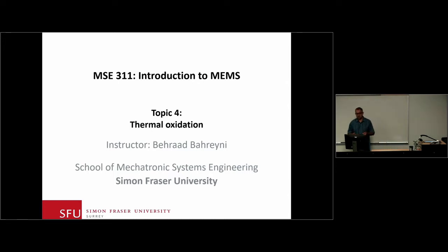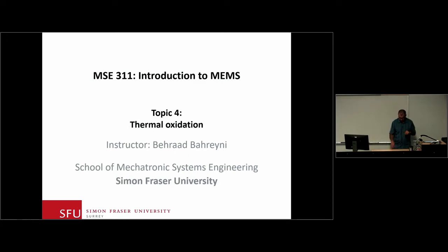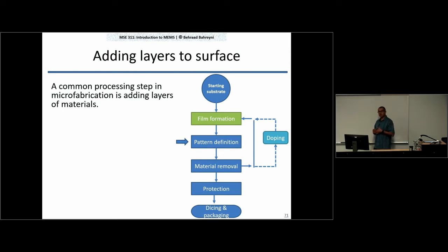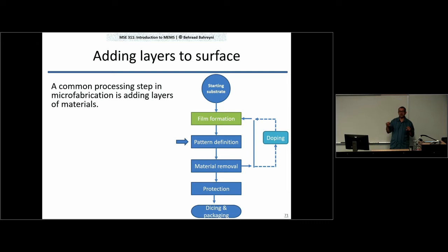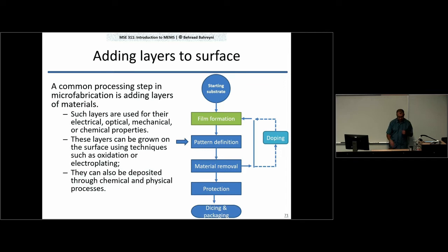In thermal oxidation, you are consuming the substrate to grow a new material film on top of it. In next lectures we'll talk about depositing other materials — even metals — onto the substrate. But for silicon dioxide, we are growing it from the substrate itself. In the sequence of process steps, this is the film formation stage. We talked about doping earlier; now we talk about film formation, one technique of which is growing silicon dioxide from silicon.